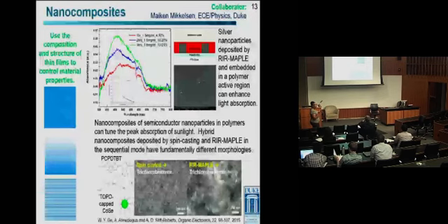So basically a gradient bulk heterojunction where along the z direction, the thickness of the film, you're changing the composition of the bulk heterojunction dynamically during growth. And that gives you a lot of flexibility in terms of controlling film properties. And then also the possibility for having basically a superlattice structure where you have layered structures of alternating materials. So our ability to make these types of structures, we think, will enable unique thin film properties. And so in this case, talking about special light absorption specifically for applications to solar cells.